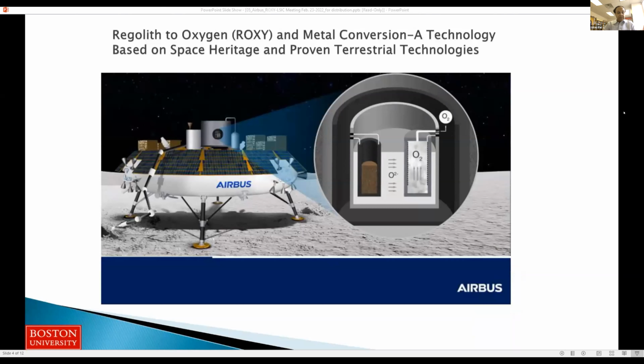One variation of this technology I'm working with Airbus is their patent pending Roxy process, regolith to oxygen and metal conversion. It uses the oxygen ion conducting stabilized zirconia-based anode structures to collect pure oxygen while reducing the regolith in porous metal cathode cup immersed in the molten halide salt electrolyte. Next slide, please.